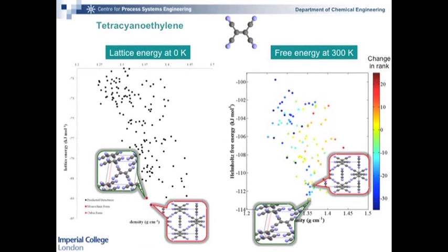Okay? And in this case, Manolis found that the cubic structure has moved up quite a bit and is no longer the most stable, and that the monoclinic structure is now the most stable, in agreement again with experimental data. So we're very excited about these results. Okay, so we're making progress to understand and predict how molecules behave in the solid, and this will help us to understand then the solid-liquid interface and how molecular structure affects solubility and how changing the solvent might be appropriate for one drug or another.